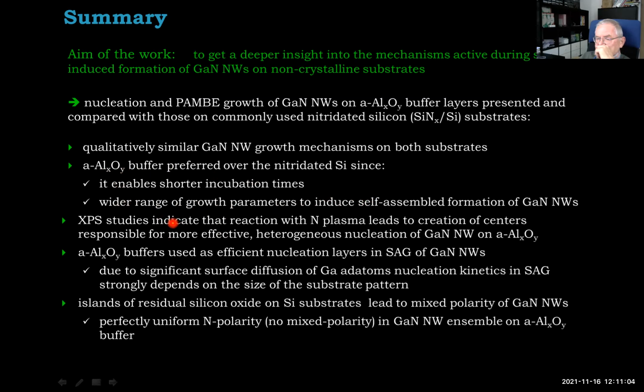I tried to explain this using experimental studies, just to get information on what centers might be responsible for this enhanced nucleation rate. Then we used these aluminum oxide buffers for SAG, and this was a good opportunity to show you the importance of surface diffusion of gallium atoms, how strongly it influences nucleation kinetics. And finally, the last topic I discussed is the uniformity of polarity of nanowires grown on silicon. In particular, the important message is that the substrate must be perfectly uniform and clean. Otherwise, if you have islands of residual silicon oxide, you may expect mixed polarity in this case.